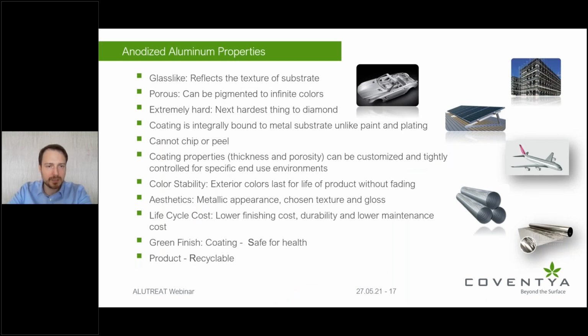So the reason why anodization is a very desired coating process, or the most common surface treatment for aluminum, is that it has many desirable qualities. It is glass-like. Basically, aluminum oxide is the second hardest material that can be found naturally without synthesis. And by converting the aluminum to aluminum oxide on the surface, you can get practically a very hard, transparent coating that is a part of the surface because it's converted from the aluminum. Therefore, it will not chip or peel, or it's not subject to filiform corrosion. But today we will also touch base on the metallic appearance because it is a transparent structure. It stays metallic. So the surface can be colored without changing the metallic appearance, which is very important for aesthetical application.